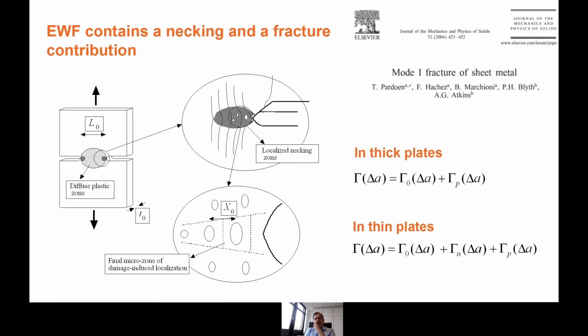So let's look again at the double-edged notch tension specimen here, with a drawing where you see the diffuse plastic zone and the fracture process zone at the initiation of cracking. And now you see a zoom of what is happening in this fracture process zone. And you see two things. First of all, in most metallic thin sheets that are sufficiently ductile, you see significant reduction of thickness at the crack. So it's really a necking process taking place at the crack tip, which dissipates quite a lot of energy. And in the meantime, if you zoom in inside the material, you see also the development of damage and cavities that are nucleating, growing, and coalescing.